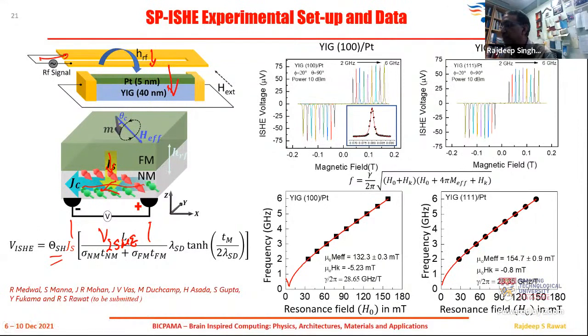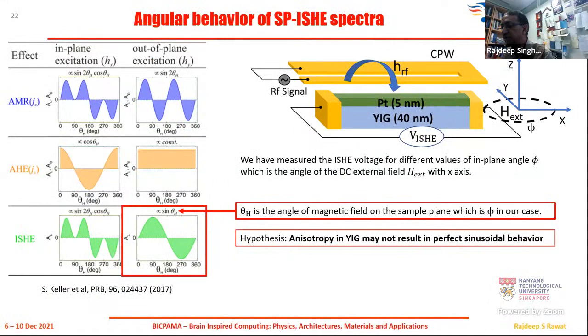So what you see on the right are the spectra that we observed for this YIG/Pt layers, but for the different orientations of YIG: 100, the one which has the cubic anisotropy, and YIG 111, which did not have the cubic anisotropy. So that is what we wanted to see, how it is going to affect. Through this spectrum, by analysis in a typical conventional way, we can derive the parameters for our films, which are listed over here. You can derive your anisotropic field values. You can find out what is your M effective and so on and so forth, which are listed over here. Again, through the Kittel equation fit.